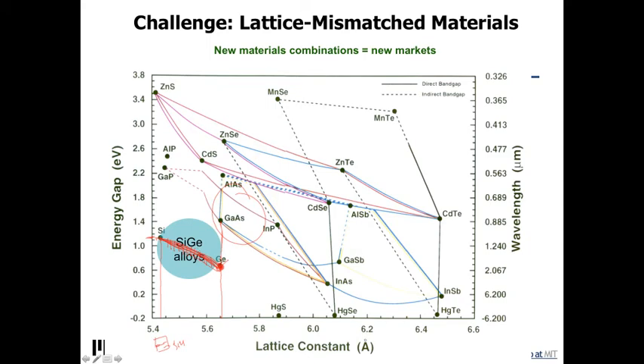However, germanium was still not quite good enough for optoelectronic devices of gallium arsenide, and we had a management change, and so we needed to demonstrate something kind of quick. And this is where Yohung and I actually got together, because I had material that was out here that was fairly good, but it wasn't out here, so we couldn't do the optoelectronic application. And so Yohung had been in a group in graduate school where some of the people had tried to create strained silicon. And strained silicon was in theory known for a long time, because in the 60s, when semiconductors were really rising and people didn't know anything about them, people put them under pressure and looked at how their band structure changes and all this sort of stuff. And from that, it was speculated that if you could have tensile strained silicon, then you could have very high mobility. And if you put silicon on silicon germanium and it was thin, you would actually get that strain. So one thing we could do is put strained silicon back on top of silicon germanium.